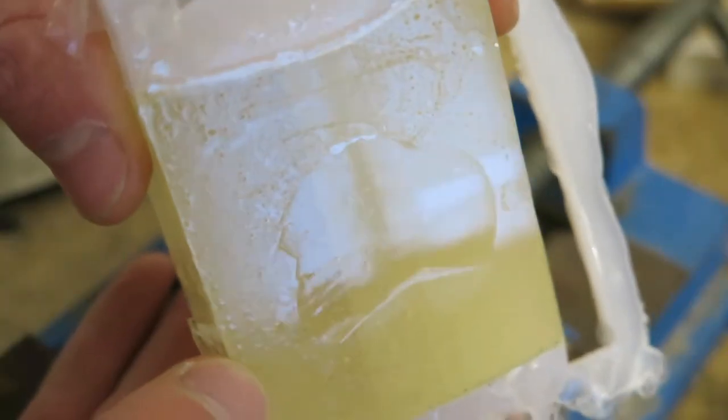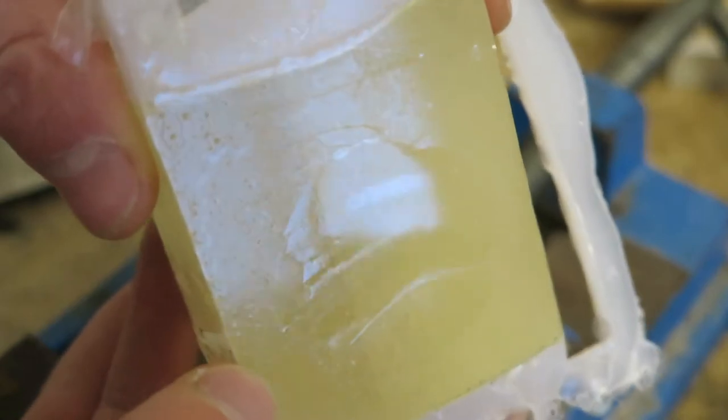When making this I was using epoxy resin that was quite cold. So there's a lot of bubbles, and basically the sliding surface is very terrible. And it also looks like that this cold resin likes to stick more to things. So I have a piece of glass tacked to my sliding block basically. And that sucks.